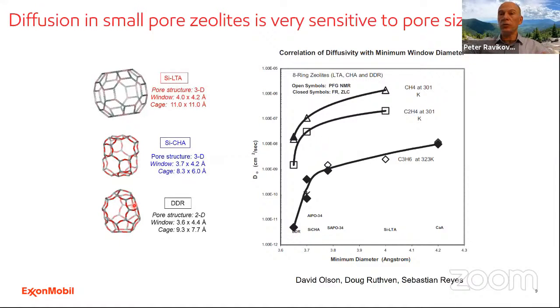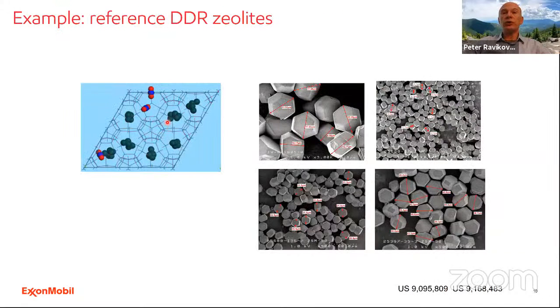Therefore, in order to be able to study this system, you need to have very accurate molecular simulations and also accurate experiments. So one of the materials which we've been looking at is the DDR zeolite, for example. This zeolite has windows of about 3.6 angstrom. And these are examples of these DDR zeolites, very nice crystals of different sizes. And this is an example of molecular simulation of, say, a methane and carbon dioxide mixture in this structure. And as you can see, windows and cages in these zeolites. It's a hexagonal arrangement of cages, and each of these cages has 3 windows to neighboring cages. So it's effectively a 2-dimensional structure in this case.